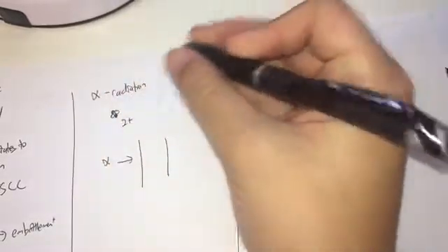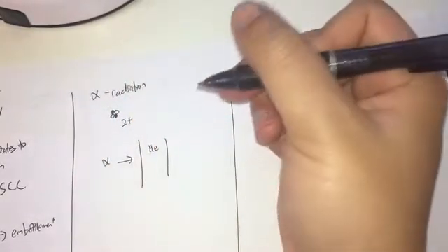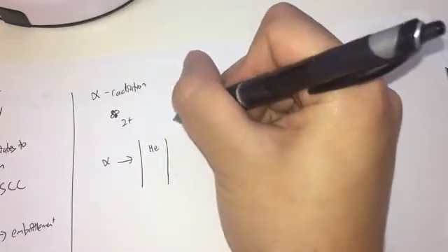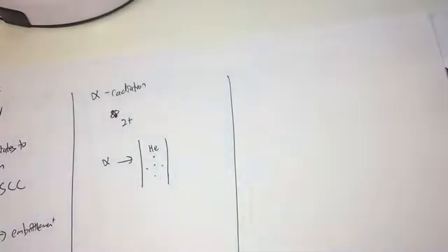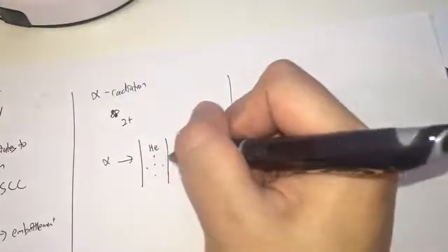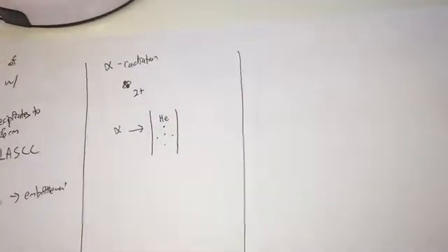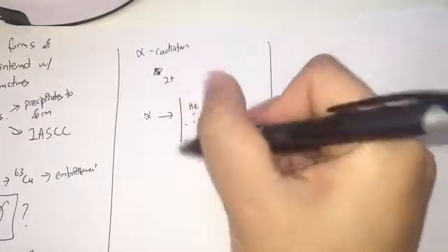So when you have alpha radiation here, you'll start implanting helium atoms into the metal, be it steel or the cladding. So there'll be some helium atoms dispersed in these steels. And like the neutron, before coming to a stop, they will deposit a lot of energy into the lattice, causing a PKA cascade, or a displacement spike.